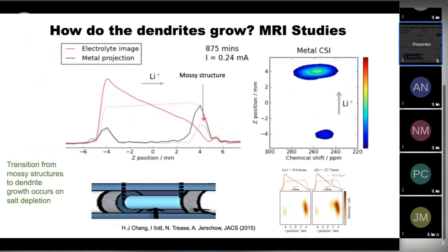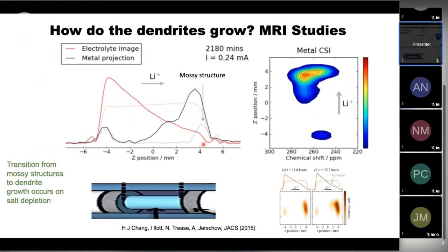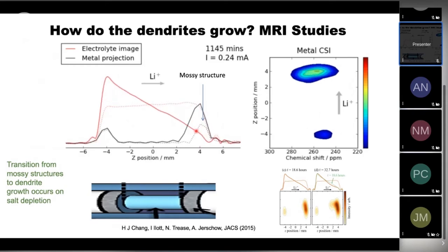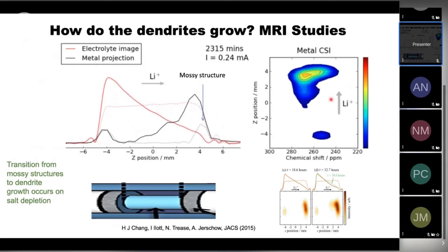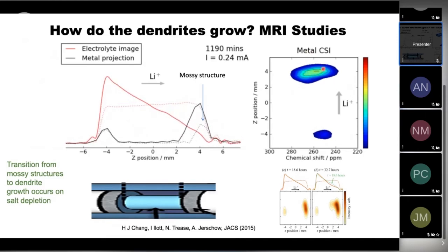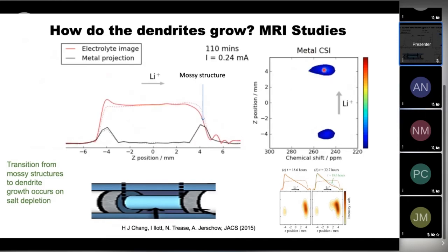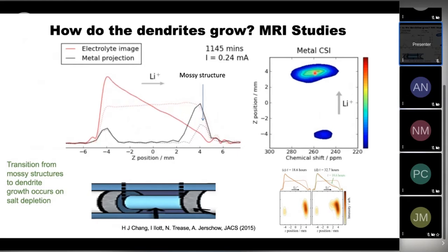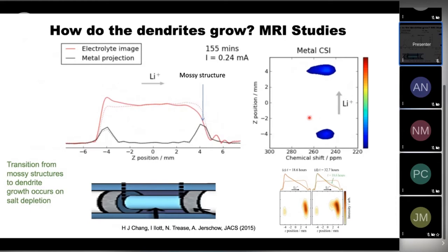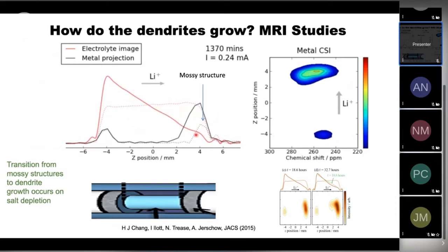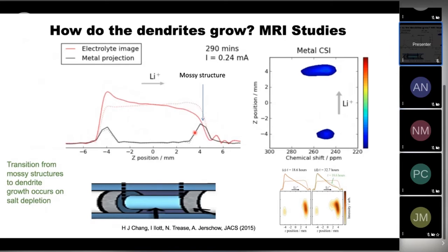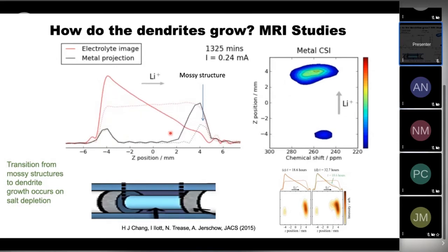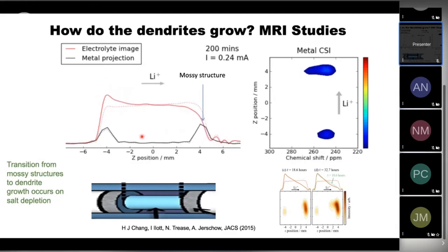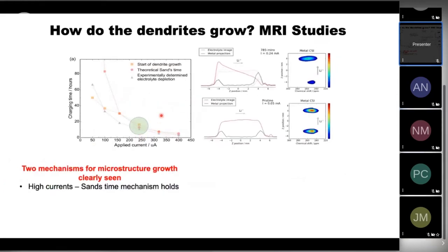Now let's watch the lithium metal. So first of all, you see the formation of this sort of mossy structure. But when the concentration drops to zero, it grows dendritic. This is more clearly seen in chemical shift imaging, which is also used in medical imaging as functional MRI. You can see the formation of mossy structures, and then it grows dendritic. And the mechanism behind this is that when the electrolyte concentration depletes and goes to zero near the lithium metal, you have a space charge or an electric field that basically drags the lithium dendrites across the structure. And this has been established before, but had not been seen directly in situ.